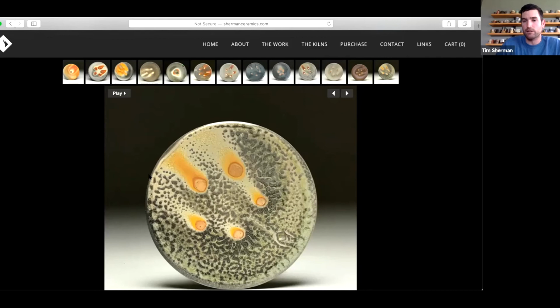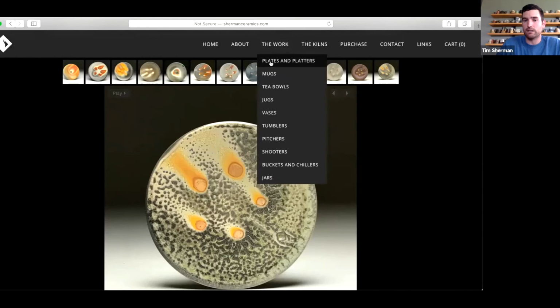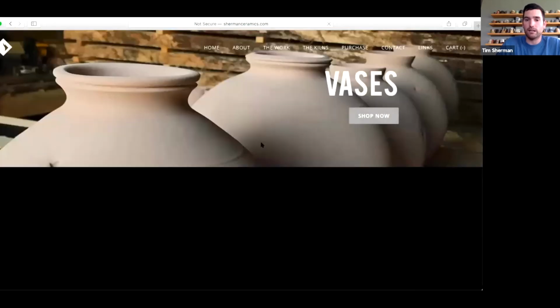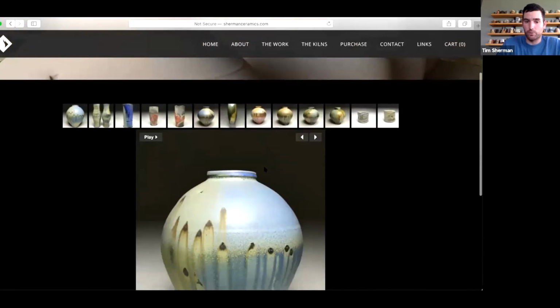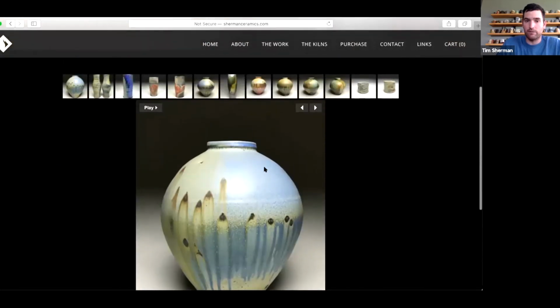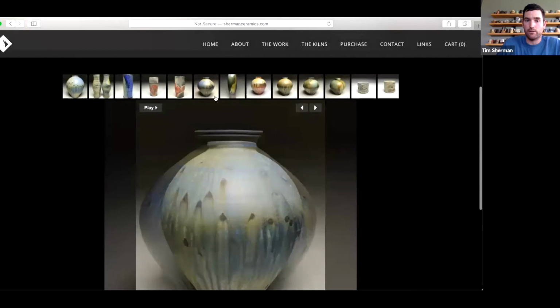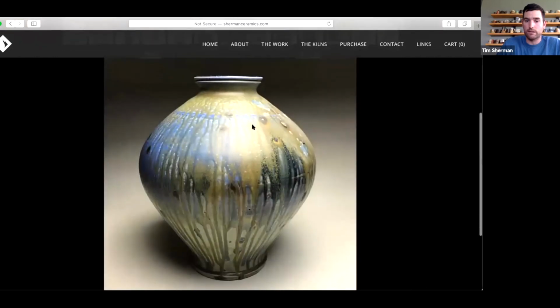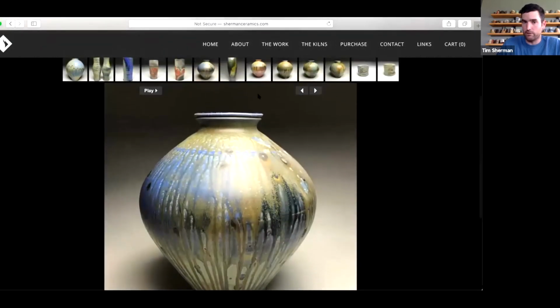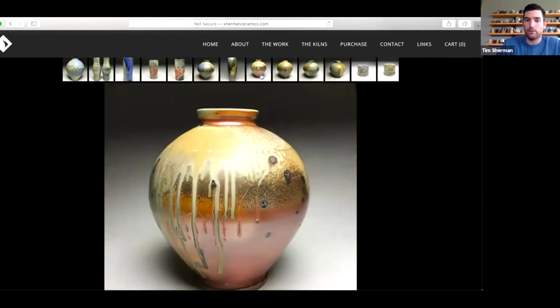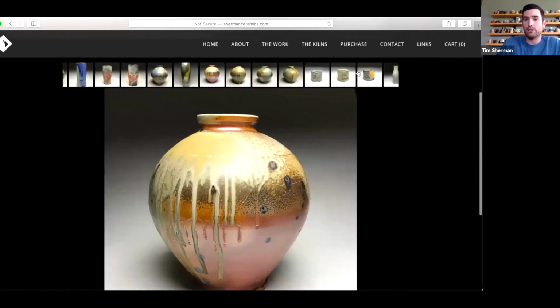That gives everything a chance to melt. And then the glaze work, the stuff that's got heavy glaze on it, I want that to be less hot for a shorter amount of time. So some of these pots that have a lot of ash glaze on them, that are really runny, drippy glazes, if they are at cone 12 for 6 or 8 hours, they will melt entirely off the bottom of the pot. So that's a real issue for me. So I do try to control that.